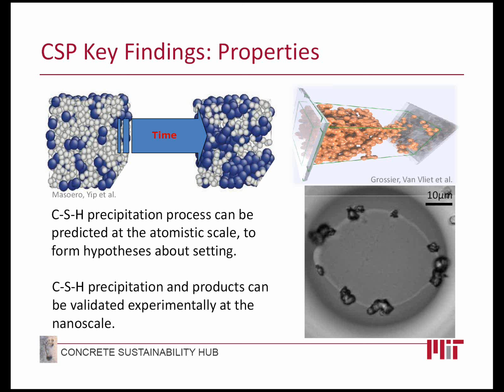And again, a very strong motivation on the concrete science platform side is not just to make computational predictions, which in isolation are not useful to industry other than thought experiments, but to validate them with experiments. So the black and white figures you see on the right are experiments that are very novel and were developed for other purposes related to drug discovery, but we've actually adapted them within the hub to study this precipitation of this key phase within the cement paste. And that back and forth between the models, which are able to predict this precipitation and setting over seconds to hours to days to months, is now being directly validated within the experimental part of the concrete science platform. Okay, next slide, please.